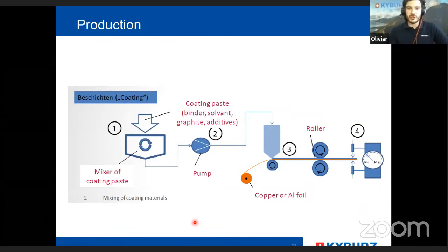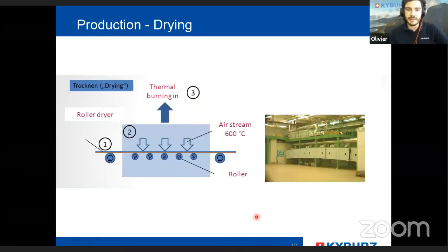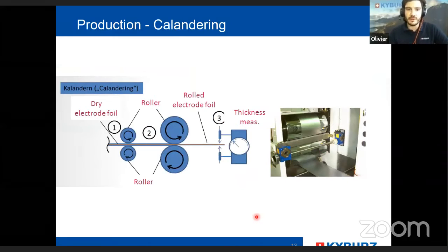And here is a very short introduction to how a cell is produced. In the first step, you mix the coating paste. Then you put the paste on the aluminum or copper foil and press them together. In the second step, you go through a drying process, then press them again and measure the thickness of the aluminum foil and the copper foil with the active material on it.